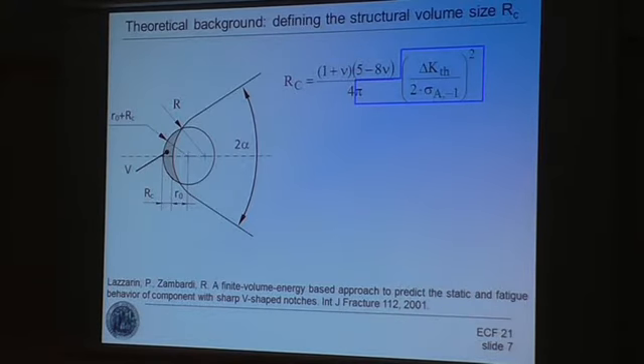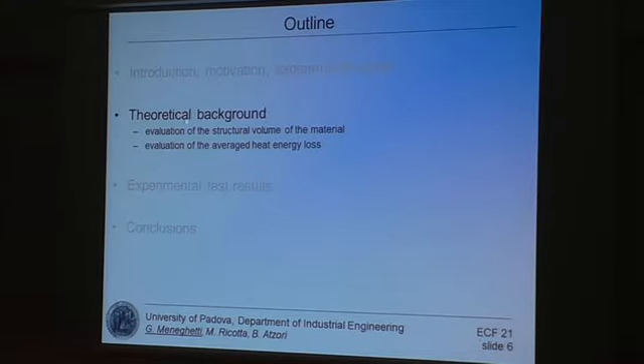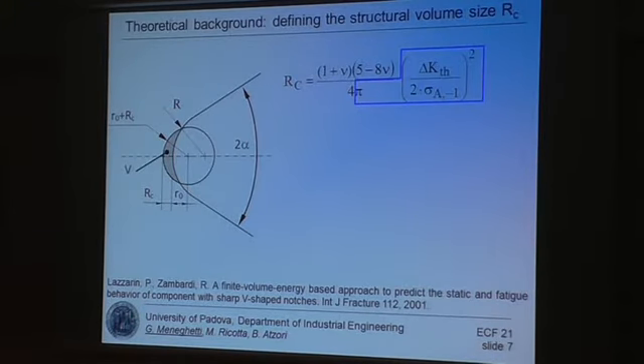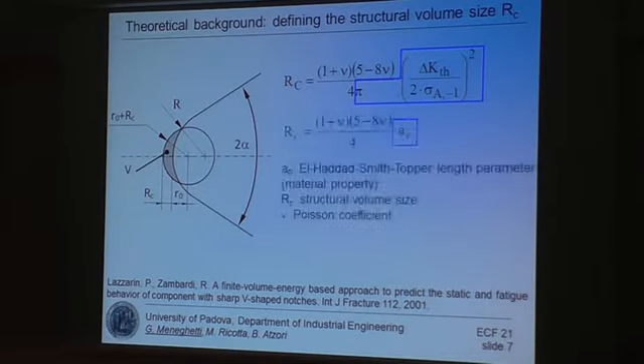Now, going back to the two main terms of the model, we have first to estimate the structural volume size. The idea was to use the proposal by Professor Lazzarin and Zambardi. They defined a structural volume size which has a slice shape at the notch tip, where the critical volume size is equal to this formula. The important terms are the threshold value of the long crack stress intensity factor and the material fatigue limit. You can recognize here the well-known El Haddad, Smith and Topper length parameter, which is a material property, and here you have simply the Poisson coefficient. The small r0 parameter depends only on the geometry, the radius of the notch.